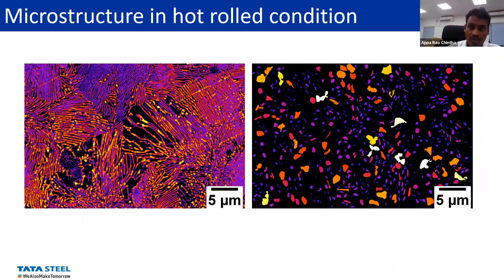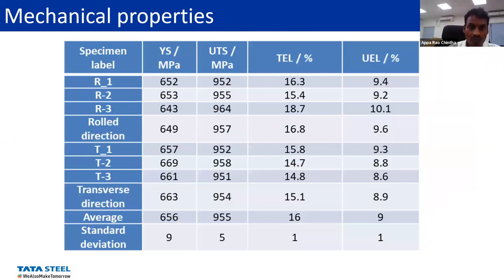At higher magnification, the color code shows the size distribution. The elongation after modifying the rolling schedule is increased from 10% to about 16% — that means about 50-60% improvement in total elongation. Strength is reduced as expected from the hardness values. More importantly, it's the elongation that's important to process the steel at the customer end.